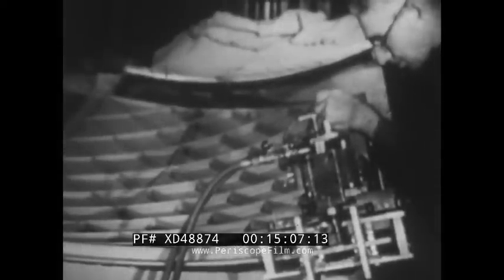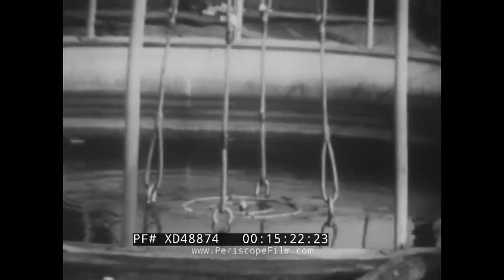One of the more interesting aspects of bulkhead fabrication is the technique used to fabricate the gores of the common bulkhead. The gores of the aft-facing sheet of the common bulkhead and aft LOX tank bulkhead consist of a thick waffle section and a thin skin. It is at the LA division in Inglewood that the waffle sections are first machined out of aluminum alloy blanks. The partially finished gores are then taken to North American's El Toro facility, where they are clamped in mirror-finished female dies. Then they are placed in a tank of water and further formed by the explosion of an exactly placed charge of primacord.